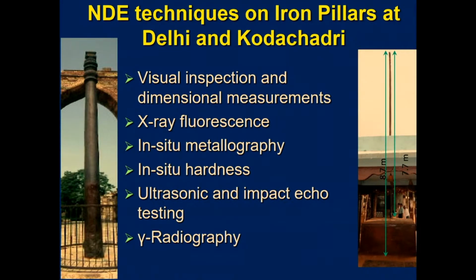Okay, this is the Delhi iron pillar. So we used a number of investigations. These include visual inspection, dimensional measurement, X-ray fluorescence, in situ metallography, in situ hardness, ultrasonic and impact non-destructive testing, and the gamma radiography. And particularly the gamma radiography has been done in the night because of the hazards involved, and also to see that the visitors are not affected by these investigations.